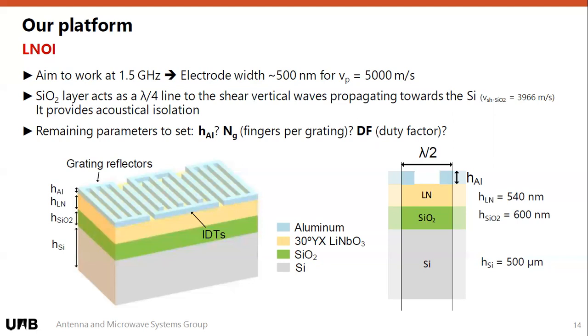We bought this wafer specifically with these measurements, with these thicknesses, so that we could work at this frequency. Actually, the thickness of this layer depends on the phase velocity of the shear waves on silicon oxide. We took this from a NIST standard. So considering this frequency, this 600 nanometer silicon oxide layer will work as an impedance inverter at around 1.5 gigahertz.